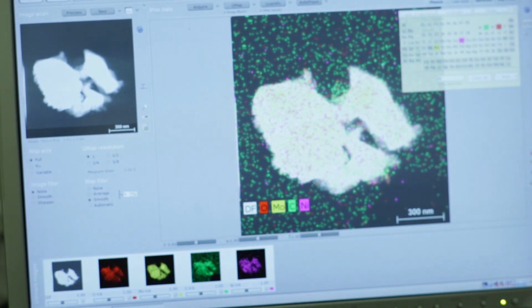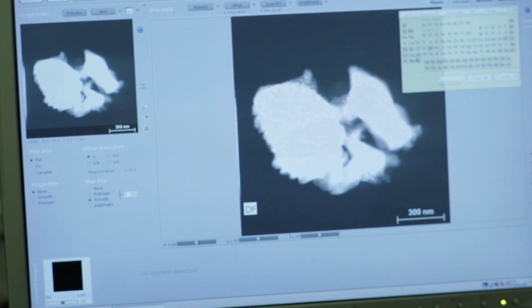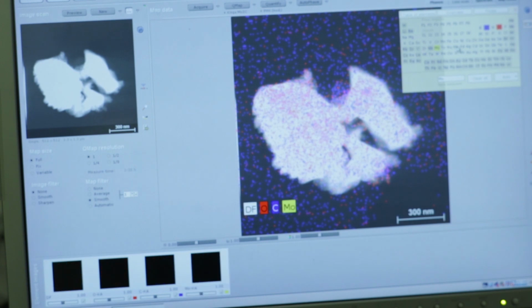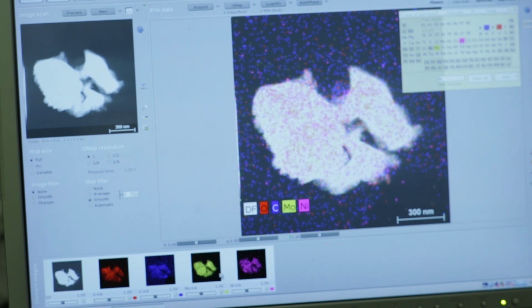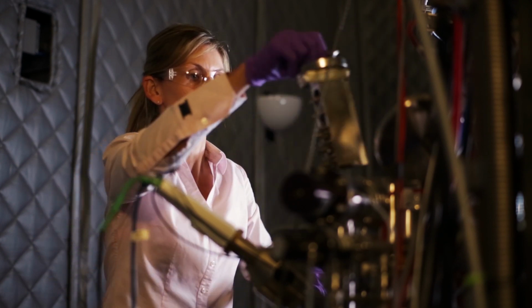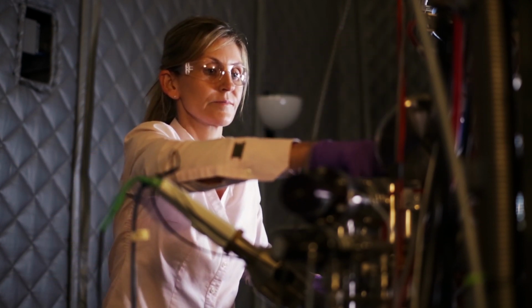In conjunction with EDX or EELS, they allow us to characterize the catalyst, and it's very crucial in catalyst development. Using spectroscopy analysis, it allows us to identify the distribution of different elements throughout the catalyst particle. It allows us to identify the clustering of the elements, what the precipitates in the catalyst are made of, and identify the core-shell formation. STEM and high-res STEM imaging allow us to capture the morphology, size, and the structure of the catalyst. High-res STEM imaging also allows us to look at the atomic level of the different interfaces, and also localize the coke formation and identify it using EELS.